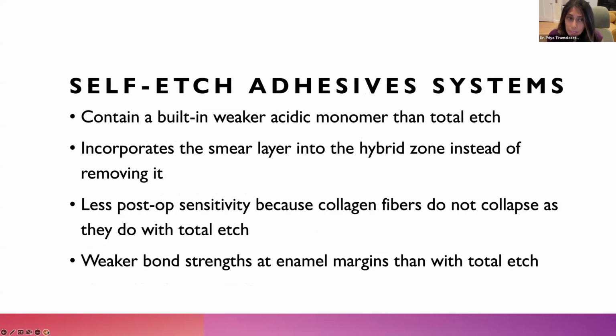With a self-etch adhesive system, it contains a weaker built-in acidic monomer than the total etch does. It's incorporated into the system, so you don't do a separate etch step, and it incorporates the smear layer into the hybridized zone instead of removing it altogether. And this incorporation allows for less post-op sensitivity because those fibers don't collapse as they do with total etch. There are, however, weaker bond strengths at enamel margins than with total etch as well.